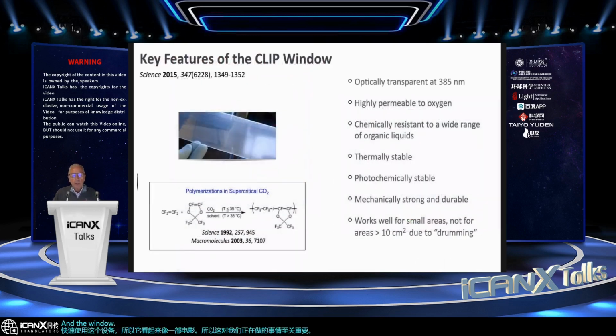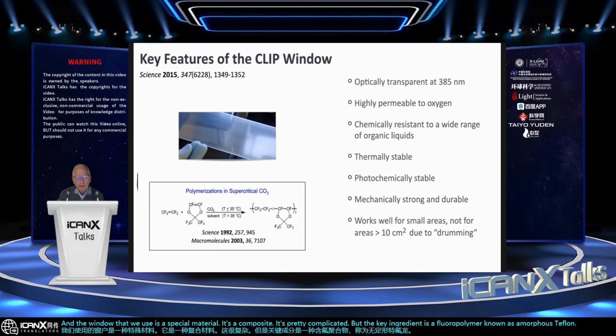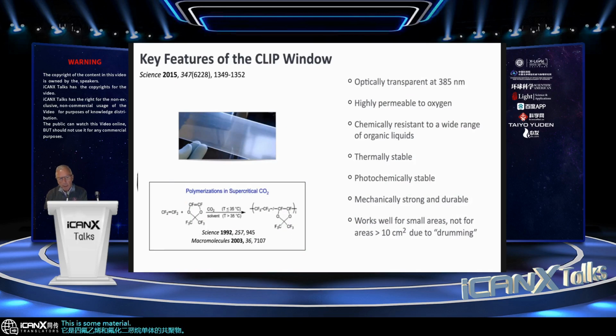And the window that we use is a special material. It's a composite. It's pretty complicated, but the key ingredient is a fluoropolymer known as amorphous Teflon. It's a copolymer of tetrafluoroethylene and a fluorinated dioxole monomer. This is a material that we worked on extensively in the early 1990s. It's an amorphous form of Teflon that's optically transparent. It's chemically resistant to almost everything. It's very thermally stable, photochemically stable. But the key is it's among the most oxygen permeable materials known.